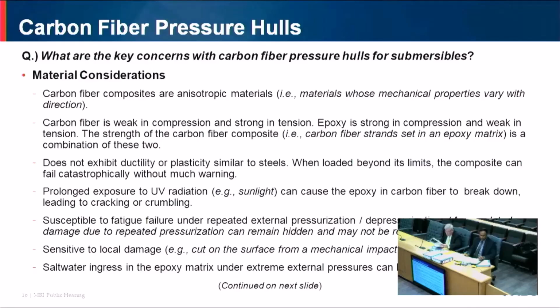And the accumulated damage may remain hidden and may not show up. Okay? So the important thing here is unless the fatigue failure shows up as cracks or delamination, you really cannot see the damage. It may remain hidden in the carbon fiber strands. Okay? So once you have a crack or a delamination, the extreme high water pressures will accelerate the growth of the crack or the delamination. And the crack will grow very fast. Okay? And then you can have collapse or failure of the pressure hull.